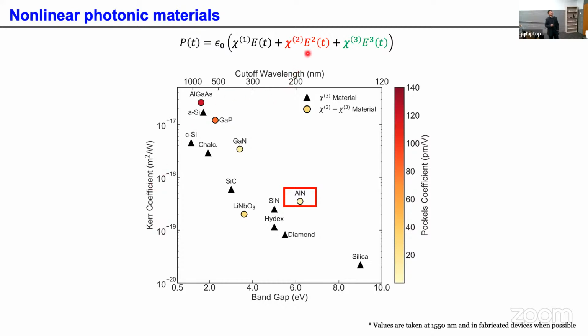A range of materials has Chi2 nonlinearity, for example gallium arsenide, aluminum arsenide, gallium phosphide, gallium nitride, lithium niobate here, and aluminum nitride. So you can see the Chi2 color coded here, Chi3 on this side, and they both invert somehow depending on the band gap, right? So if you want a large nonlinearity, choose a narrow-band semiconductor. Of course, that will cause problems: you have multi-photon absorption, and in a lot of cases you really want to avoid two-photon absorption, three-photon absorption, or this higher order photon absorption.